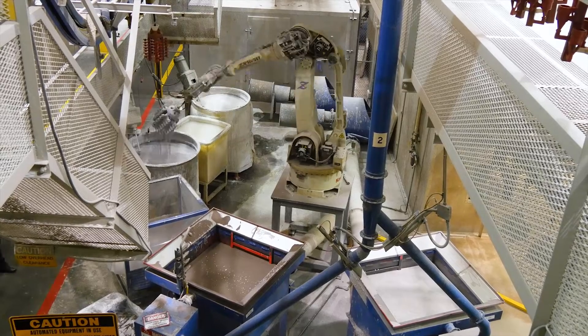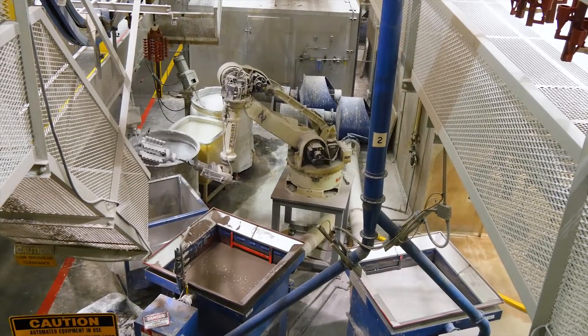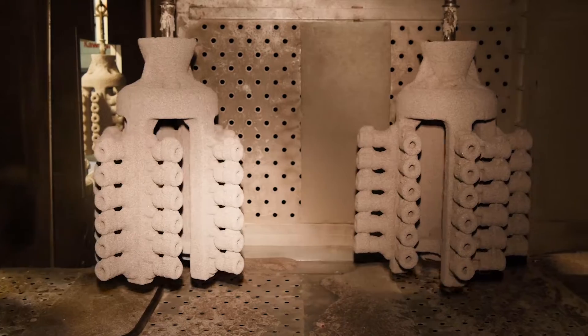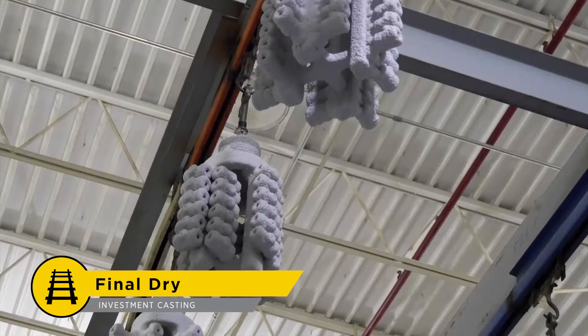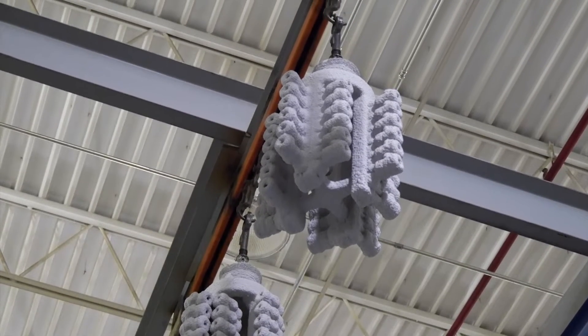The trees are kept on a strict schedule, constantly dipping, drying, re-dipping, and re-drying in a carefully regulated environment to create defect-free ceramic molds. Any deviation can result in mold cracking. Once the molds have completed their dipping and drying cycles, they are moved to an even more strictly climate-controlled room to complete the drying process.